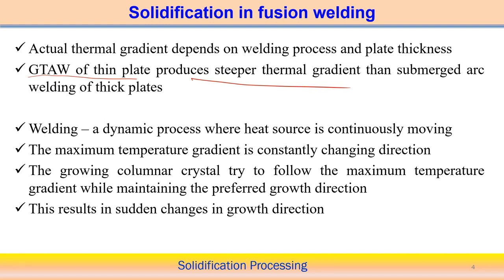If you remember, we always try to explain the solidification behavior in terms of the solidification parameters G and R. Based on that we can explain the solidification behavior in the welding process. But overall, the welding process is a very dynamic process since the heat source moves continuously in one particular direction. So the maximum temperature gradient is constantly changing in direction depending upon the movement of the heat source.